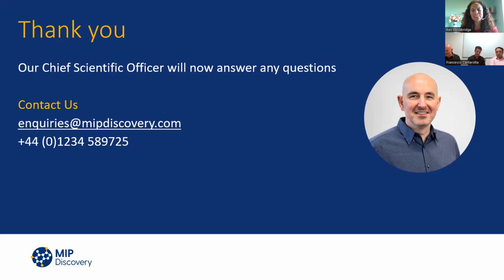Jessica. Well, if there is absolutely no functional group, so we're talking about alkane or alkyne chains, then technically the chances of getting high affinity nanoMIPs are quite slim, because as mentioned in one of the previous slides, you need to have functional groups interacting between the monomers and the template itself. If the template is simply made by carbon and hydrogens, there is very little that you can exploit there.